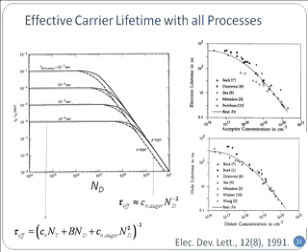But experimentally, I have shown you from 2 different papers that indeed at high density, this is 10 to the power 20, very high density, right? 1 atom in every 100 host atoms, and you can see how the things are falling off. So if I give you a curve like this, by looking at the slope and the intercept, you should be able to calculate back the Auger recombination constant. And from the lower values, you should be able to calculate the number of traps.